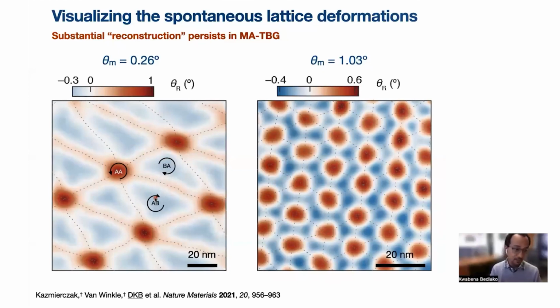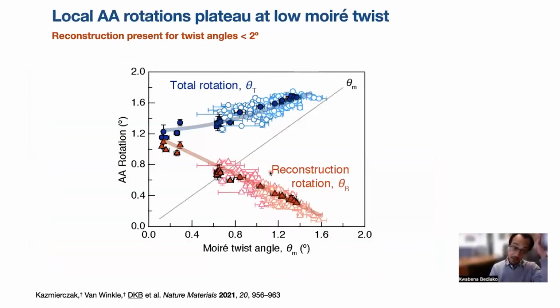But what we were able to do, because we can quantify this relaxation, is plot the local AA rotation. In other words, if you were to put blinders on and didn't know about what the Moiré twist was, and you just measured the local twist between one carbon atom and the next, and between the two layers, we can measure that as a function of the global Moiré twist, and that's this blue curve here.